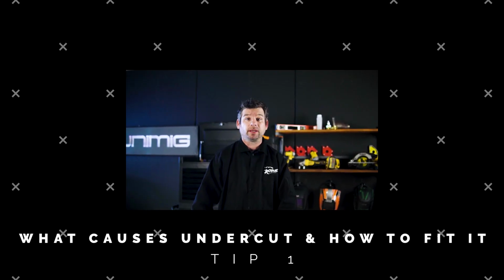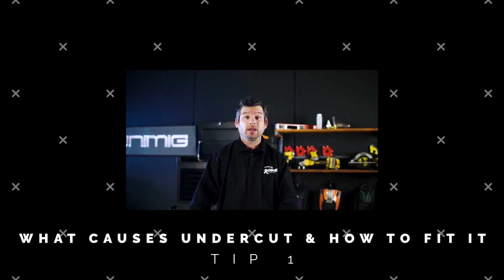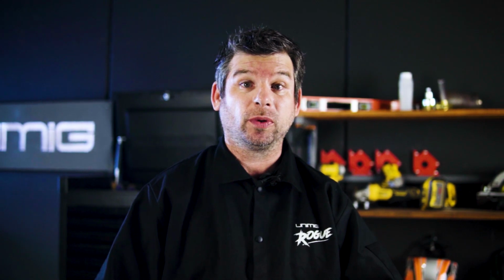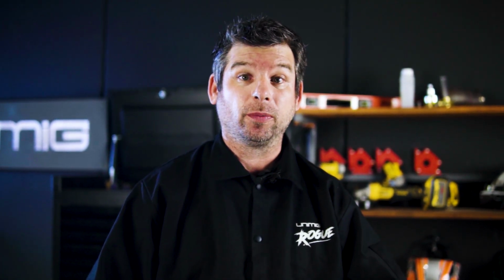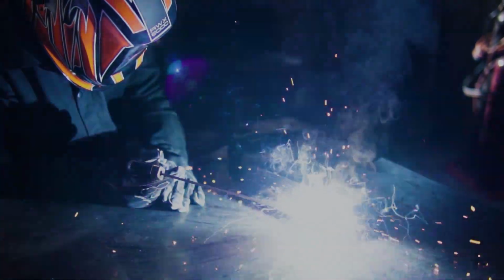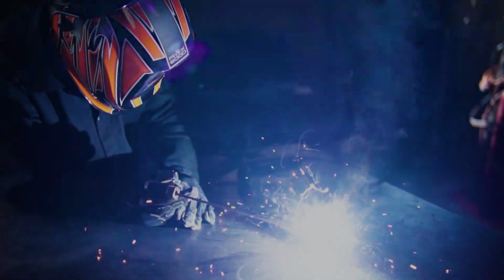We're going to be talking about another common weld defect known as undercut, the causes and how to stay clear of this issue. Undercut is caused by too much heat in one area, always formed at the toe of the weld, where the weld metal hasn't filled in the groove, resulting in a weaker weld prone to cracks.